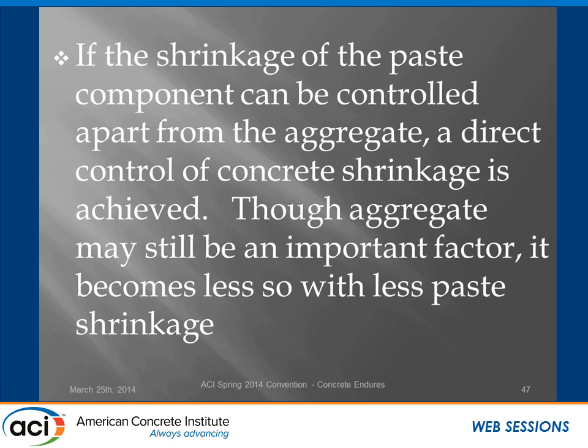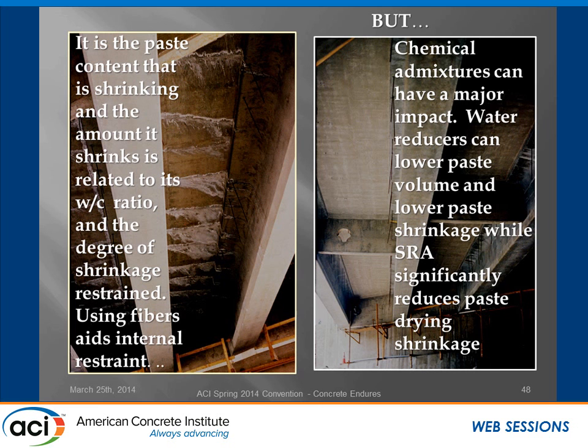So here's where we're at now, though. Barring something like that, it's the shrinkage of the paste, and if we can control the shrinkage of the paste, then we can control the shrinkage of the concrete itself. The aggregates still play an important role, but they become less and less important as we can control the shrinkage of the paste. If we can get the paste to shrink to zero, the aggregates are irrelevant as far as shrinkage goes. It's the paste content that's shrinking.